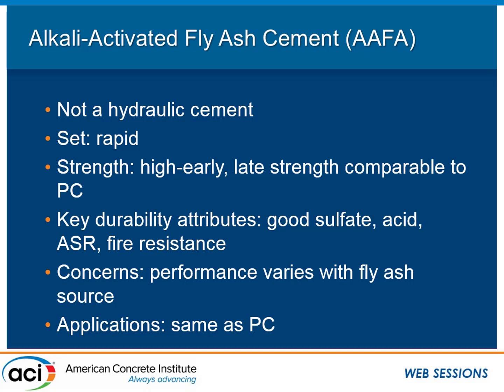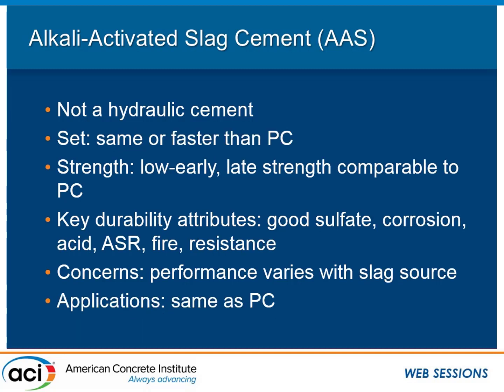So I would say fly ash geopolymers are probably the material that you hear most commonly directly compared to Portland cement concrete. Alkali-activated slag: slag, of course, typically has more calcium than Class F fly ash, where you do need to consider the amount of calcium when you look at what kind of activator you would use.